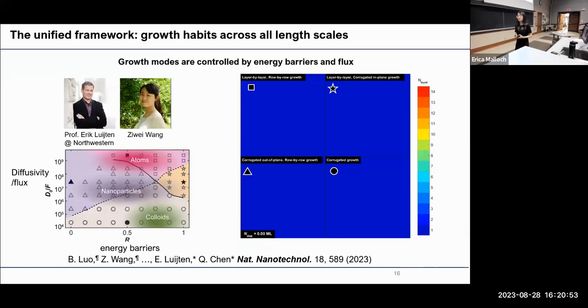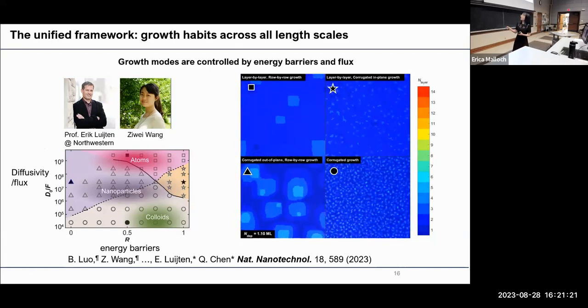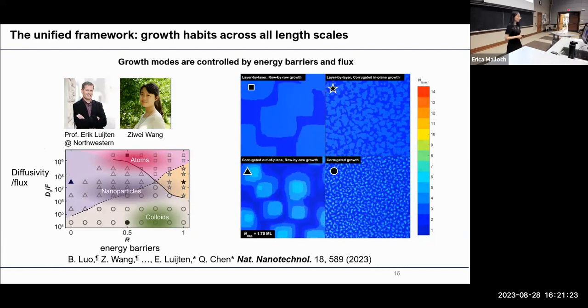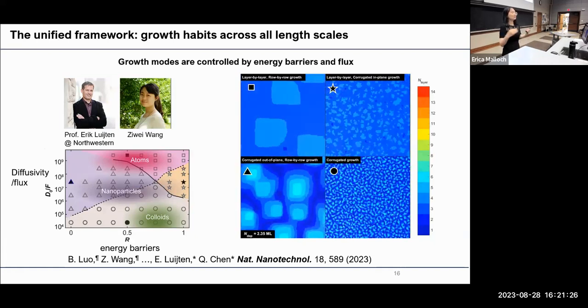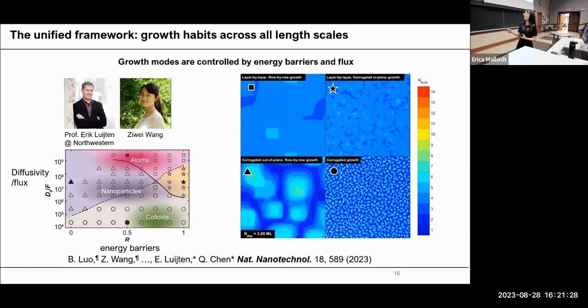With all those experimental observations and literature, we started to have this ambition to try to establish a unified framework considering the effects of different size building blocks. So that's when we went to collaborate with Professor Erik Luijten of Northwestern and his former PhD student Ziwei Wang. Together they run a lot of kinetic Monte Carlo simulations, and there are 2 highlights. The first is they're able to reproduce all the 4 growth modes that we experimentally observed. And second, they're able to sample a large parameter space to generate one phase diagram.